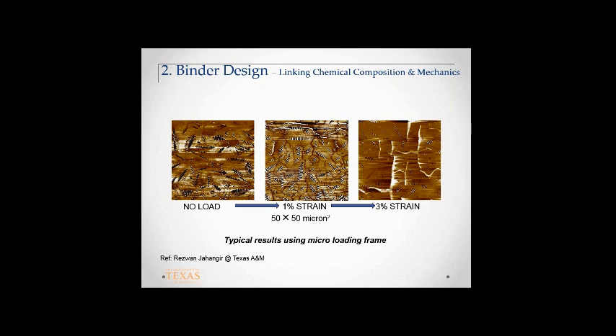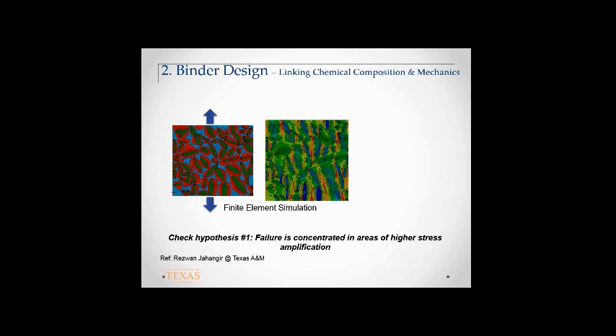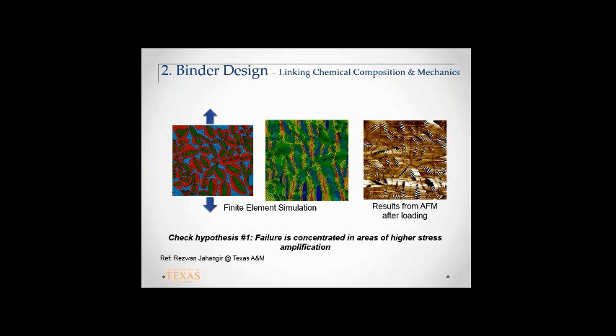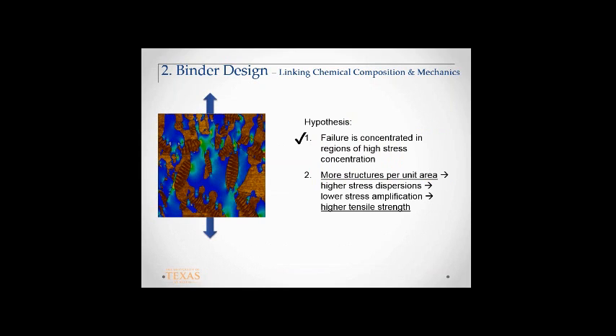But we know that some of these discontinuities start, and the interesting part is they start in the exact same place where we thought they would start, where we said that you have these stress concentrations right next to these boundaries. And you can verify that using a finite element simulation. If you take that same geometry and run the simulation again, you will see that these red locations are where you have stress amplification taking place, and those are also the same places where these discontinuities occur. So that was the first hypothesis. Seems like I give myself a check mark, but it's still carefully treading on whatever evidence we have.